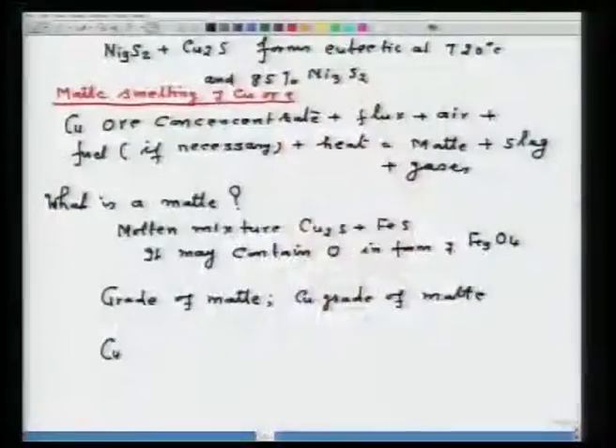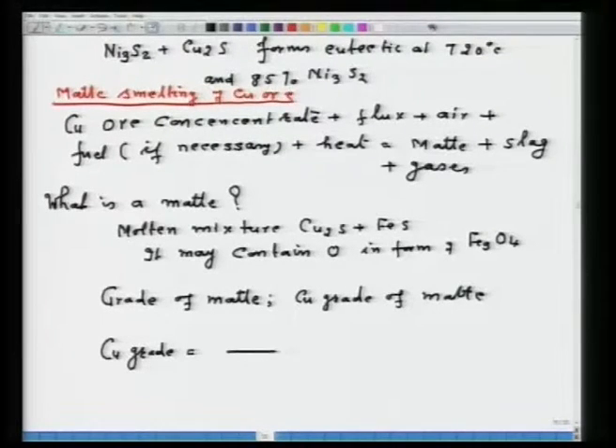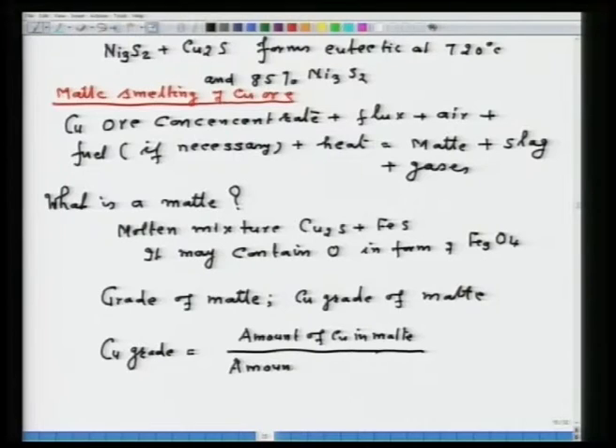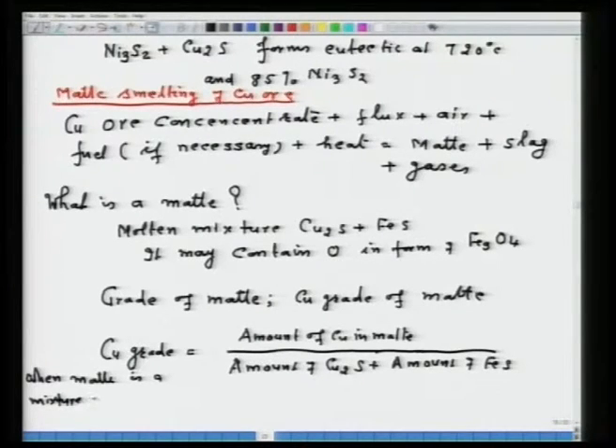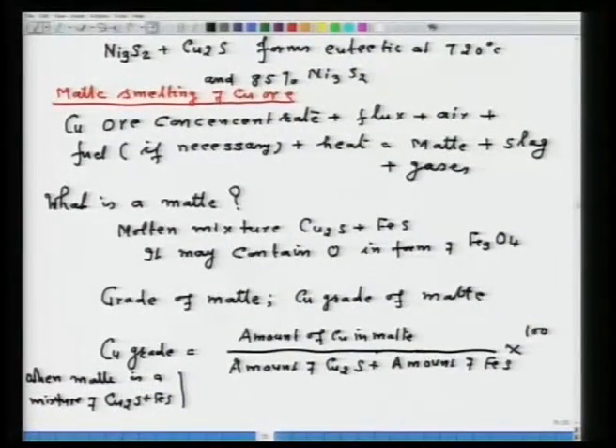So, for example, copper grade can be defined as the amount of copper in matte upon the amount of Cu2S plus the amount of FeS. This is the copper grade when matte is a mixture of Cu2S and FeS only. If it has Fe3O4 also, then it is the amount of copper in the matte upon the amount of Cu2S plus the amount of FeS plus the amount of Fe3O4, into 100. That is how you will define the grade of matte. It is given in percent.